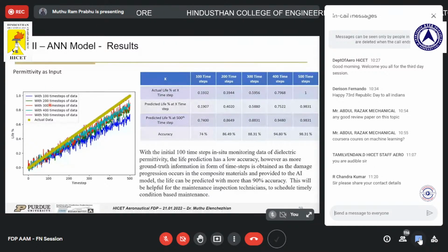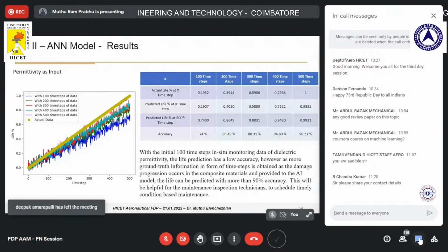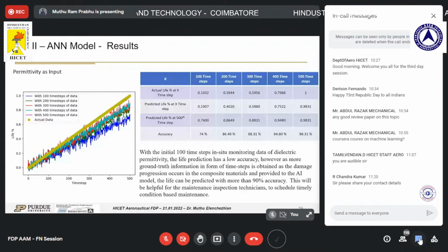And as you get more data and information about the material's health, you provide more data to the structure. As you slowly provide more and more data, your prediction accuracy increases, because as we saw from the damage behavior, you do not know the complete damage state or damage behavior in the beginning itself. You will mostly know accurately when it's about to end, almost at 75 to 80% of your life. And that's a typical behavior of composite materials. So this is what we observed when we used permittivity as the input.